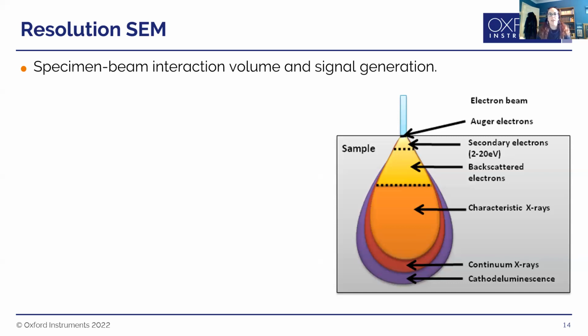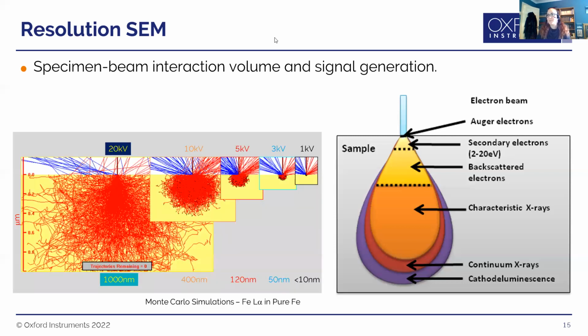And you may have better electron resolution than you do X-ray resolution because the X-rays are coming from much deeper within the sample. Now you can control this by looking at your accelerating voltage. And this is a Monte Carlo simulation in iron, really showing what the trajectory of the different electrons are when they hit the sample, when they come from 20 kV, 10 kV, 5, 3, or 1. And you can see the volume massively decreases as you go down in kV.